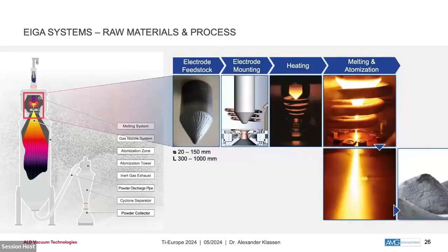The raw material or pre-processed material is an electrode feedstock. Here it's just a rod with a conical tip. This is introduced into an induction coil that heats up the rod, and the melt stream that forms at the tip of the rod free falls through a nozzle without having contact to any other elements of the machine, and is then gas atomized using an inert gas stream.